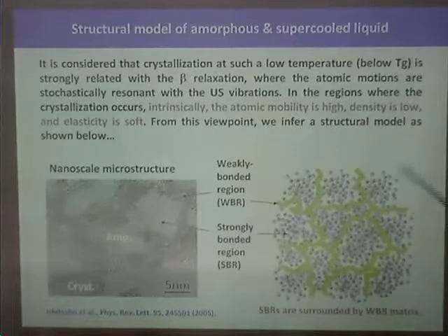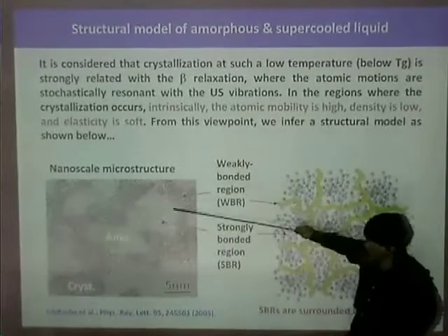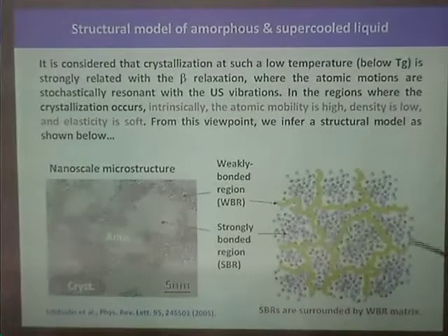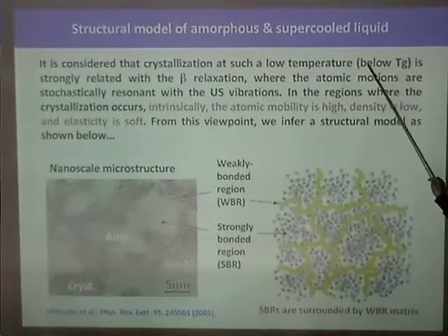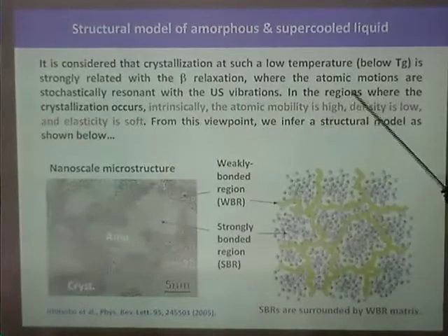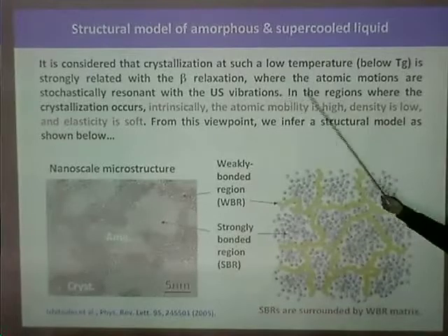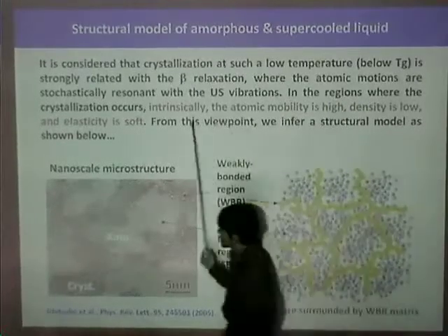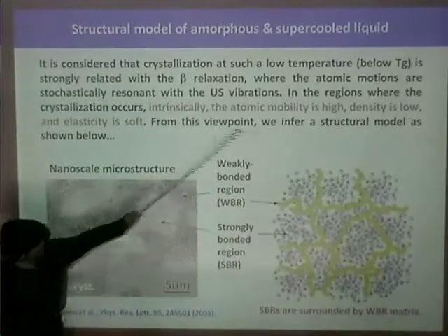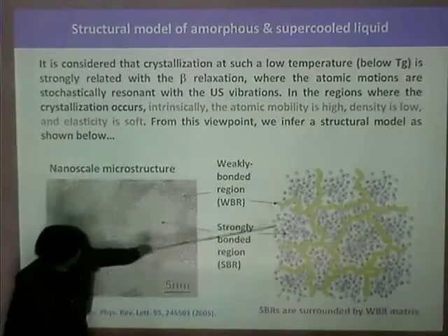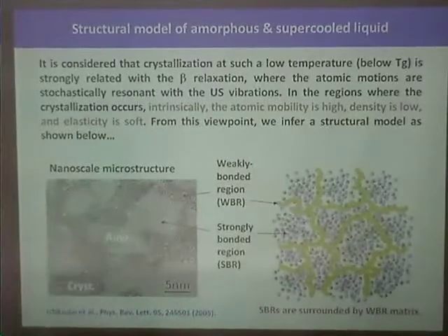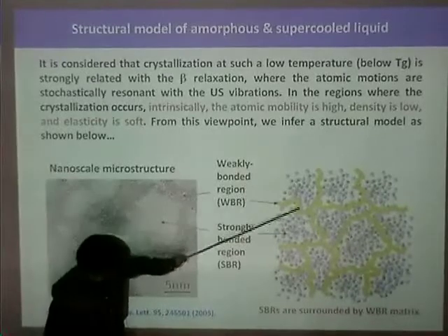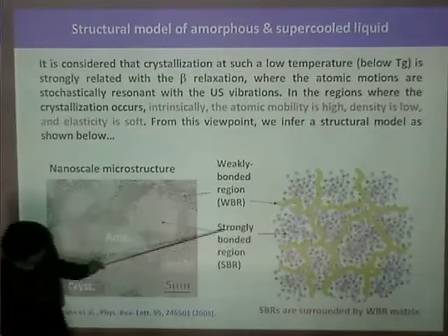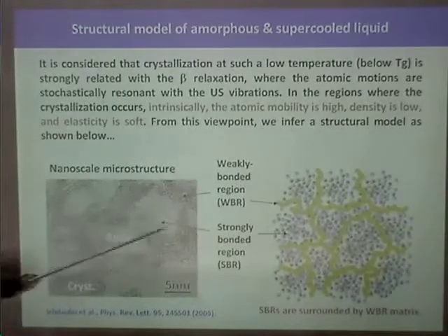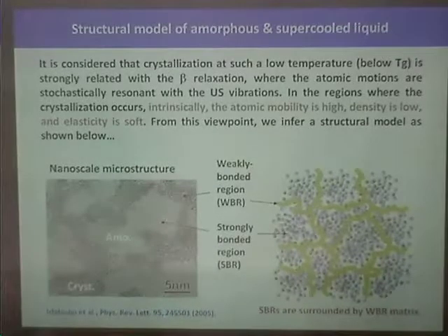From the observed microstructure, experimentally, we have proposed a heterogeneous structure like this figure. It is considered that the crystallization at a low temperature, just below Tg, is strongly related with the beta relaxation, whereas the atomic motions are stochastically resonant with the ultrasonic vibrations. In the region where the crystallization occurs, intrinsically the atomic mobility is high, density is low, and elasticity is soft. From this viewpoint, we infer the structural model shown below. The yellow part is a weakly bonded region, and this is a strongly bonded region. Like this, this is a static heterogeneity of these metallic glasses.